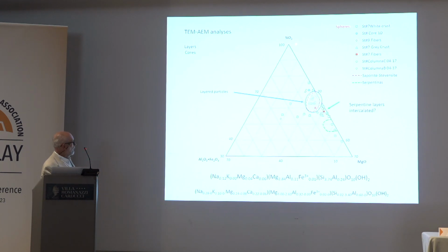But the samples are in general enriched in magnesium or enriched in aluminum. And this is particularly interesting because the green square corresponds to this sample. It is what we call a white crust. The white crust corresponds to the spheres. So we said that the spheres were precipitated in a confined environment, and this could confirm this hypothesis, because the fluid circulation is restricted, is not the average, and could be responsible for this dispersion.